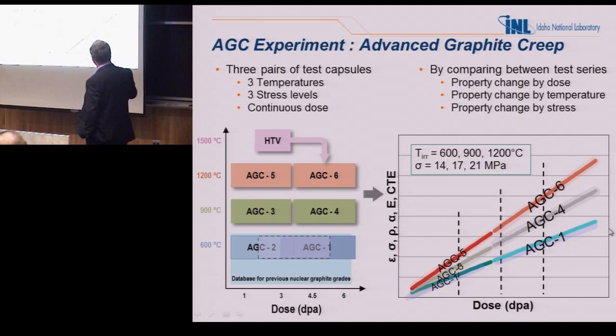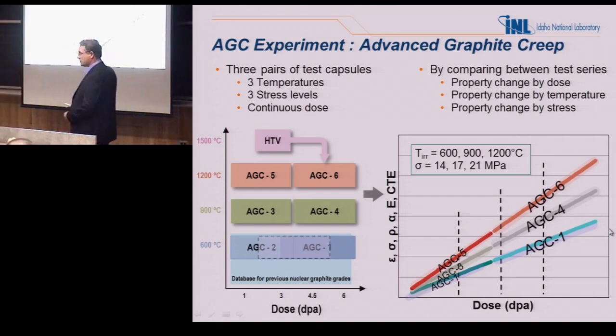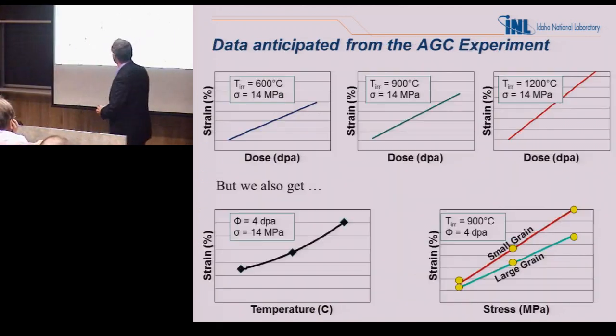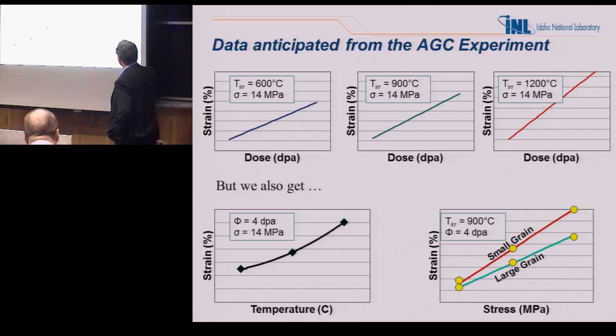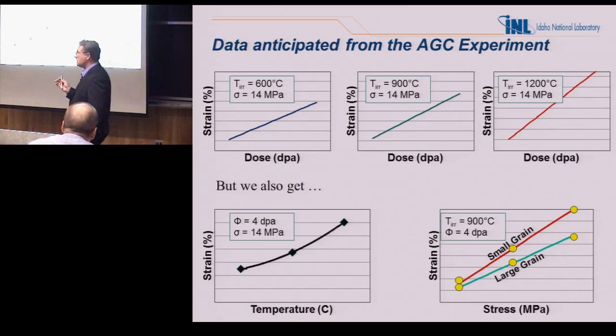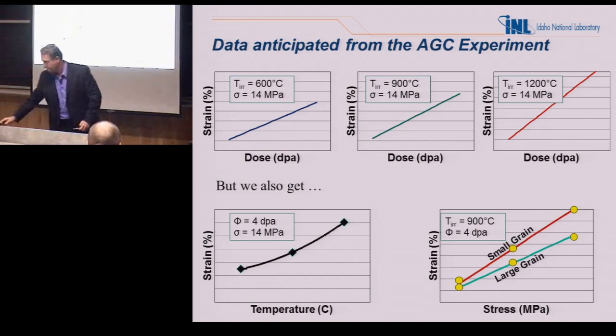So this is what's going on. These are the temperatures and the dose, and this is sort of what we're hoping to get. We want creep, we want strength, we want density, we want the conductivity, diffusivity, the stiffness modulus, and of course expansion as a function of dose and temperature. So we can go in and get the creep rate as a function of the temperature, but we can also get something like the strain that's going on. We can get the dimensional change. We can start to get the strain versus the temperature, strain as a function of stress. We can also do this for all the other types of material.